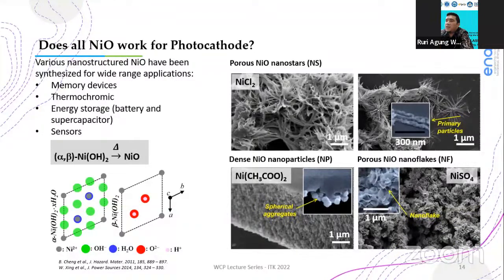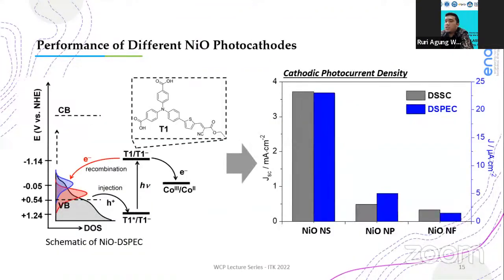To have a quick test here, we check the cathodic photocurrent generations using different nickel oxide nanostructures that we have synthesized before, and then we record the photocurrent generations using benchmark organic push-pull dye-sensitized nickel oxide photocathodes in either dye-sensitized solar cell or dye-sensitized photoelectrochemical setup. As we can see here, there is a significant difference between the performance of nickel oxide nanostars and the other structures. And then we might raise the question why it is so different.